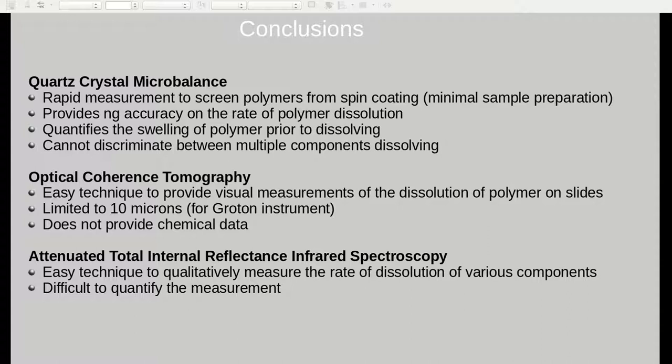To understand the dissolution of complex or multi-component systems, we used ATR. This technique was able to differentiate the dissolution of three different components in the crizotinib mixture. It should be cautioned that at this time it is difficult to fully quantitate the ATR measurement. Therefore, it should be used more as a semi-quantitative screening of the dissolution of the multi-component mixture.